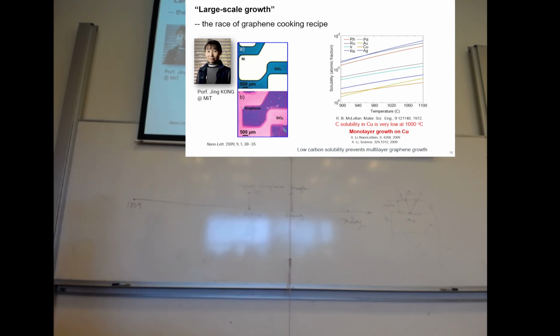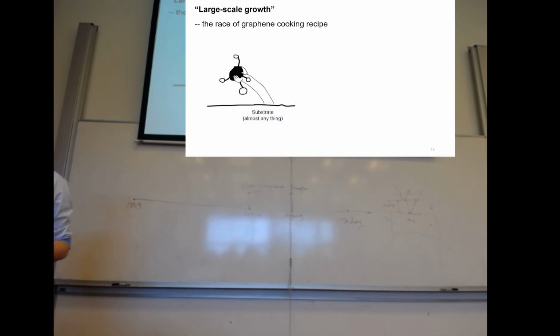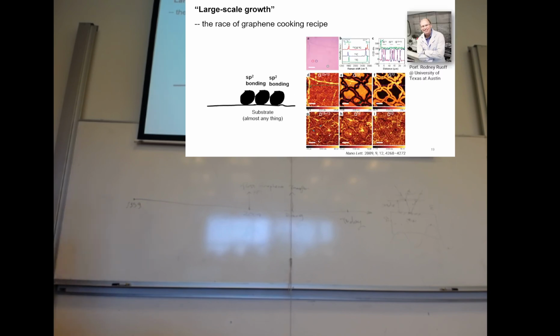So then people found that maybe if you grow graphene on top of copper, it might be better in terms of thinner layers, and that's indeed what people found. So this is the cartoon. You can see that the methane is decomposed by the 1,000 degrees C temperature, then it sticks to the substrate. Now it's almost anything, but at that time it was only nickel, copper, gold, iridium, things like that. And then the carbon adatoms will form these sp2 bondings to form a homogeneous graphene layer.